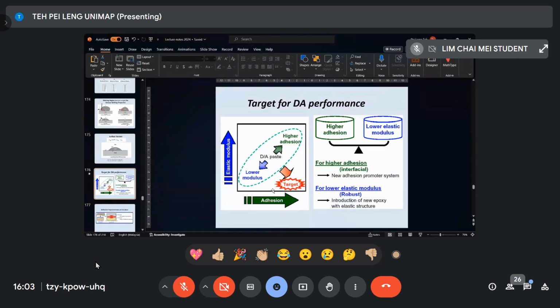If your modulus is too low, then your adhesion is low. So it's not good, right? Although you can absorb the stress, delamination will cause defects. So the perfect target will be this one: good adhesion, high adhesion strength, but low modulus. Cannot be too hard. Too hard, you can cause die crack. The stress has no place to go, so it goes to the die or to the substrate. The substrate is harder than the die. As I say, the die is very, very thin, thinner than your substrate. The substrate has how many layers, you know? The die is weaker than your substrate, of course. It's very fragile, so you will have die crack. So the bond is already broken, how to function?